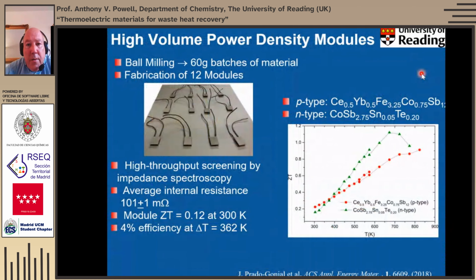So we went on from that and started thinking about, well, if we're going to use these, we need to be able to scale them. And this is where the ball milling became important, because we started preparing batches in 60-gram batches. That allowed our collaborators at the University of Cardiff to produce batches of modules, 12 modules out of a 60-gram batch of N and a 60-gram batch of P type material. They also developed a high throughput screening technique to check these modules rapidly, because module construction is a major technological challenge in its own right. And they found that across the batch of 12 modules, the internal resistance was about 101 milliohms, but only varied by plus or minus 1 across the batches.